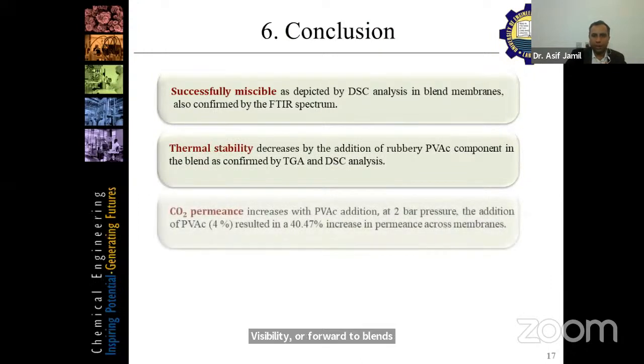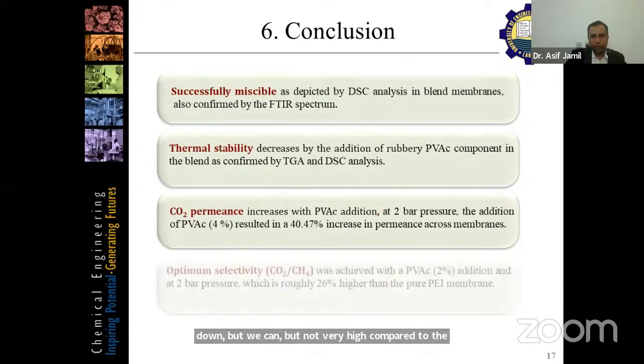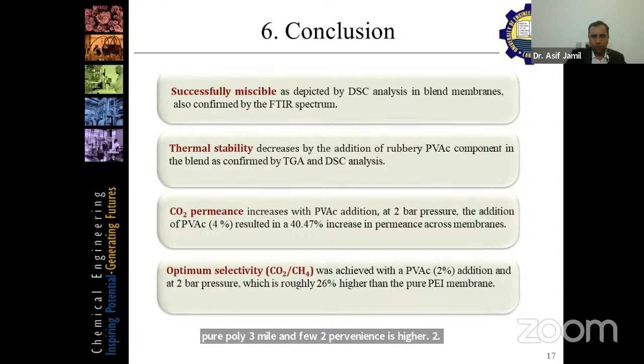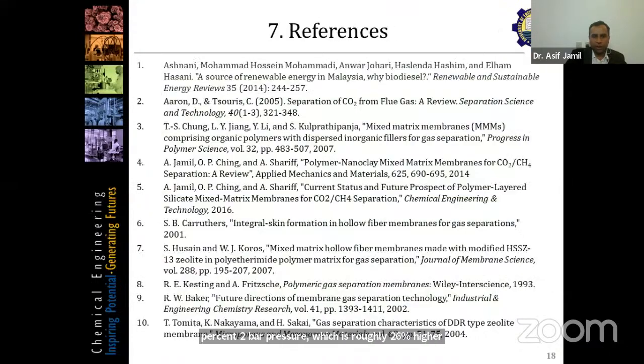And for thermal stability, we got a single Tg, and thermal stability goes down, but not very much compared to the pure polyetherimide. And CO2 permeance is higher at 4 weight%, which is a 40% increase, and the optimal selectivity we achieved at 2 weight% at 2 bar pressure is roughly 26% higher than polyetherimide. So this is all from me.